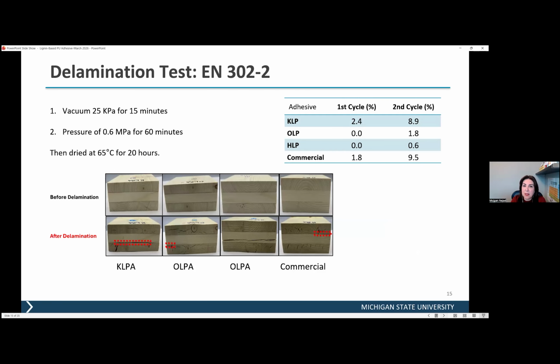Another test that is extremely rigorous, and they only do it for structural adhesives. They usually don't do that for plywood or OSB or other products, but for mass timber, it is designed to do that. Basically, you put these samples in an autoclave under vacuum and really high pressure. And based on the EN 302 test, we have to do 2 cycles.